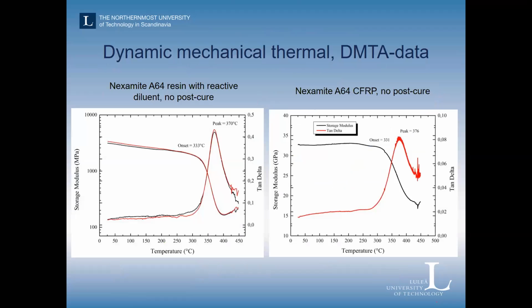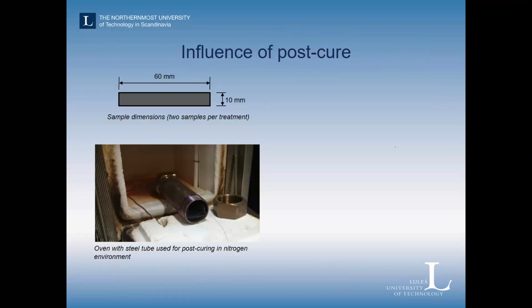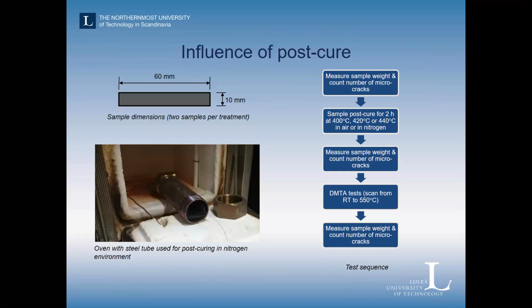We run DMTA characterization to characterize the thermal properties, and we see that we have some materials that are behaving like we're expecting, with a Tg of around, in this case with no post-curing, an onset Tg of around 350.